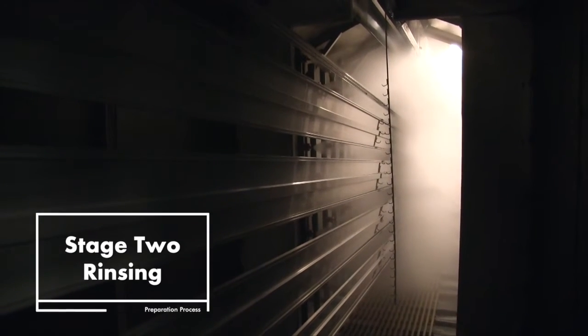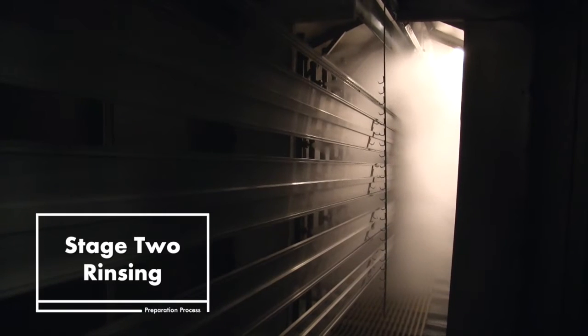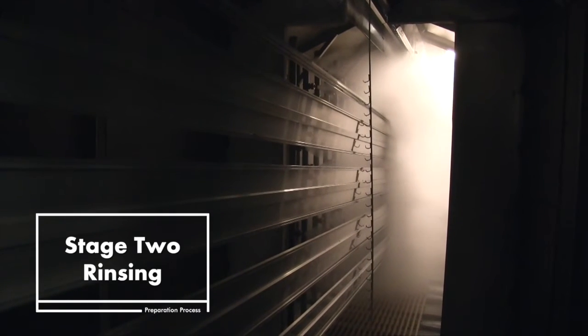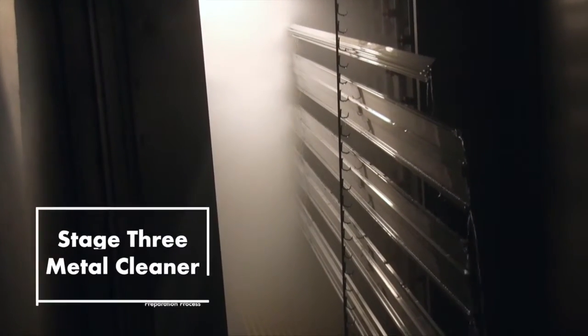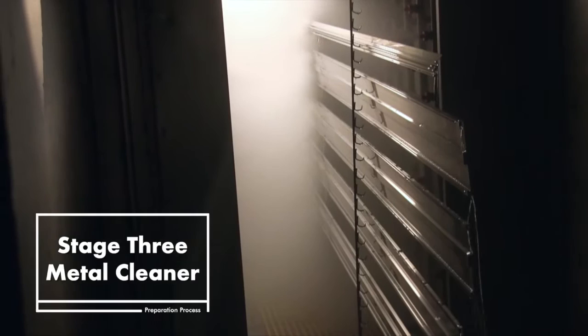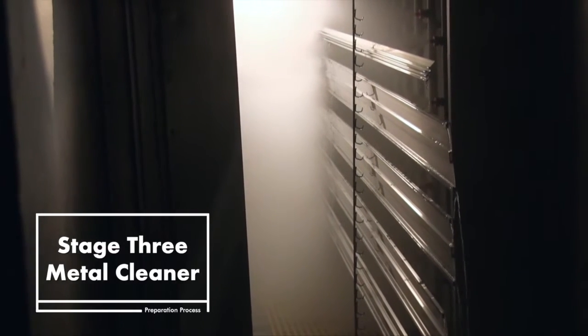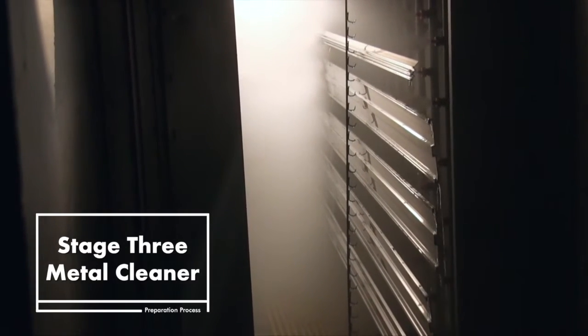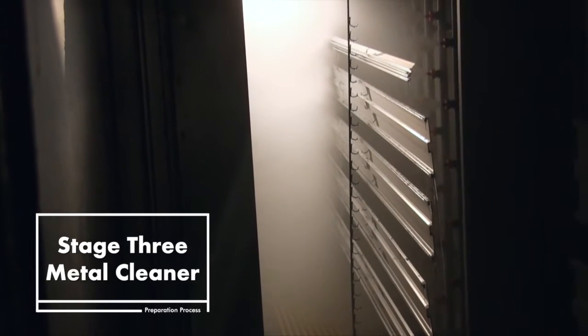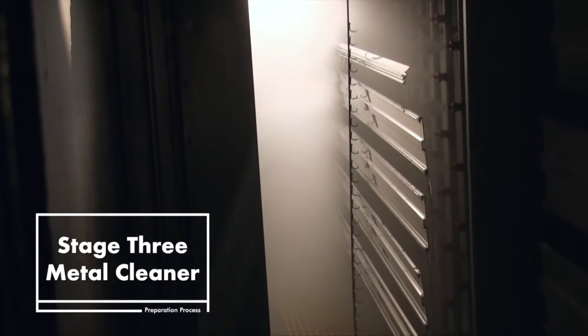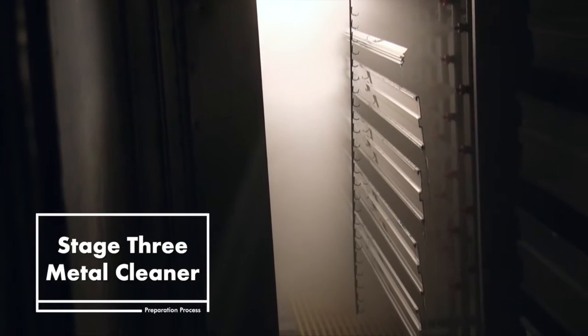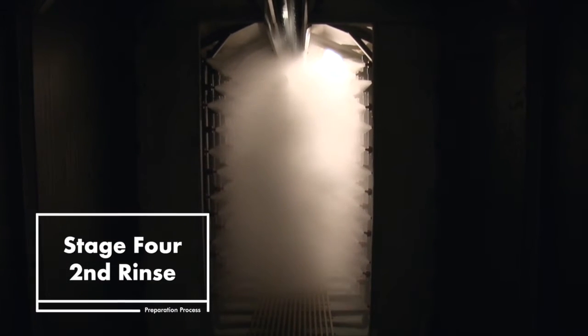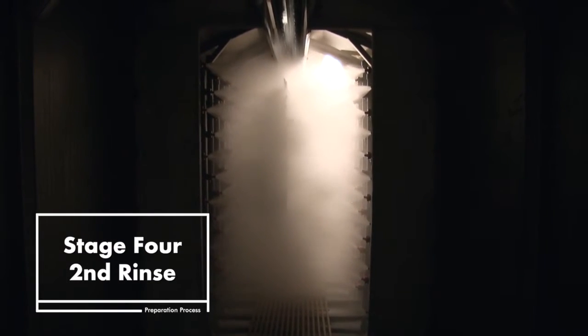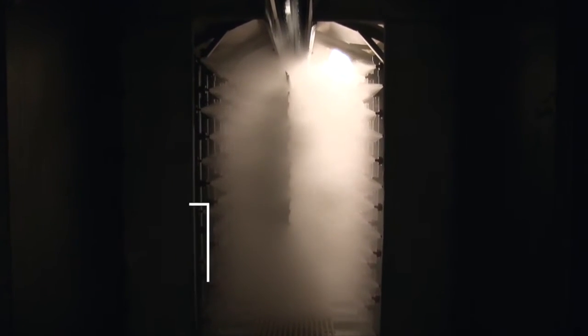Once washed, the aluminum enters Stage 2, where the material passes through a rinsing chamber in order to remove any residual cleaning agents from the aluminum surface. Next, during Stage 3, an acid-based metal cleaner and oxide remover is used to continue the conditioning process of the aluminum surface. This solution, when applied, also etches the aluminum surface to enhance the bonding process when the powder coating is applied. Once this process is completed, it'll pass through a second rinse tank during Stage 4, and then it moves on to Stage 5.